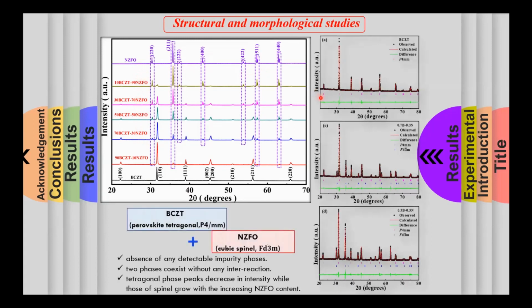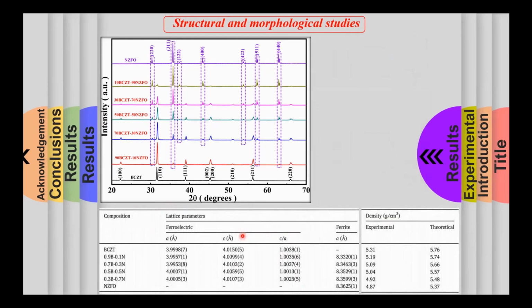Rietveld refinement of the XRD data was also performed using a two-phase model, with the perovskite tetragonal P4mm space group for the piezoelectric BCZT phase, while the cubic spinel Fd-3m space group for the nickel zinc ferrite. And using this, the refined lattice parameters, the tetragonal strain in the piezoelectric phase, and the theoretical density of the composites were also estimated.